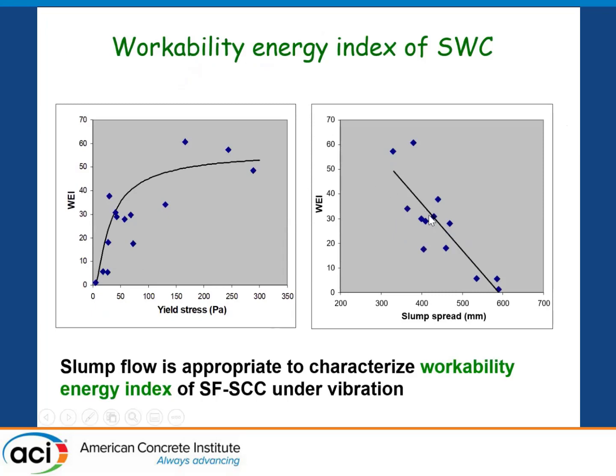But you can also, here on the right side, you can see that there's a good relationship between the slump flow, and again, it goes from about 400 to 600 when you reach this workability energy index. So when you reach SCC consistency, you don't need consolidation, or if you need it, you need very little consolidation. But as you relax it down to 20 inches, 18 inches, you definitely need that consolidation to achieve the mechanical properties.